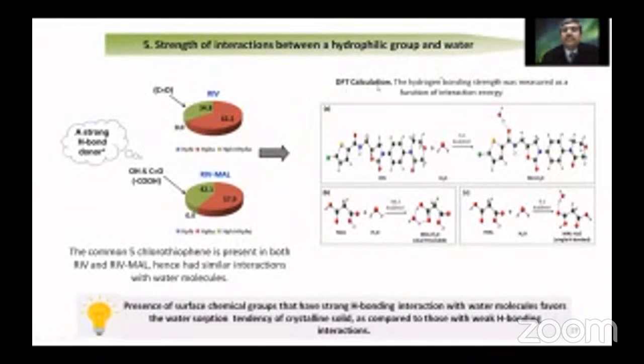This was studied using the DFT calculation, which is the density functional theory, and the hydrogen bonding strength was assessed by calculating the interaction energy between the various molecules and water. In the case of rivaroxaban, the interaction with water is associated with an energy of minus 5.1, while for malonic acid, the interaction with water at this particular COOH group is a much stronger interaction because it has a lower energy of minus 10.2 kilocalories per mole. Similarly, the interaction of malonic acid with water at this position, that is the carbonyl position, also comes up with a stronger interaction with respect to the rivaroxaban and water interaction.